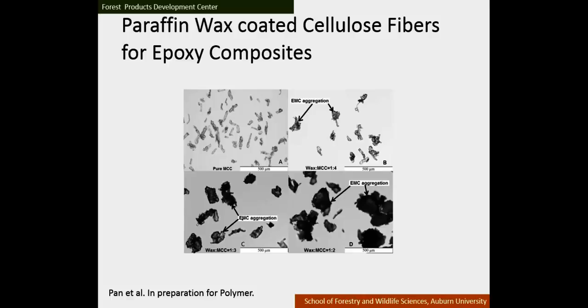And so what we did here was we just took paraffin wax. The industry doesn't use paraffin wax, but they use the slack wax, and they distribute the wax in the OSB. The wax is to help keep the moisture, to retard the moisture. And so we thought, well, if they're adding wax to OSB, then maybe you could use the wax as a carrier for the cellulose. And then the wax could keep the cellulose from bunching up against each other and agglomerating.